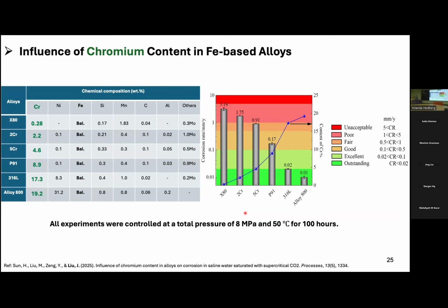The next part is we try to focus on different chromium levels. Now, I think it was 2024 when we went to the AMPP New Orleans conference. They were asking what kind of grade can be safely used in this scenario, in the water-rich phase scenario. And most people were asking, are we going to be crazy to use stainless steel or a lower chromium level? So we did a series of chromium levels from X80, which is a pipeline grade, increasing to 2 chromium, 5 chromium, P91, and 316, and even crazier, 800. We noticed that at least you need to use P91. The good thing is most of the current casing steel is P91. I don't want to go into more detail in this area. So these three alloys we present here follow this monotrend.